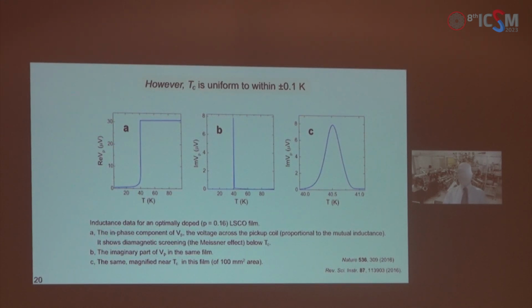In my group, as I said, we can measure the magnetic penetration depth with an absolute accuracy of 1% using the mutual inductance technique. What you see in the real part is the Meissner effect, and in the imaginary part there is a dissipative peak that occurs near Tc. And the point here is that in our best film, this peak is very sharp, implying that variations in Tc are less than 0.1 Kelvin, and that's over an area of 50 millimeters squared.